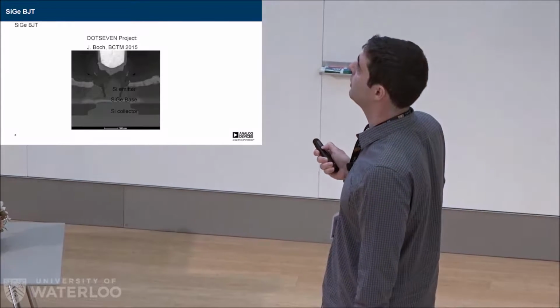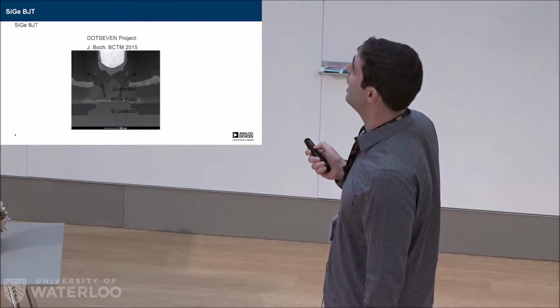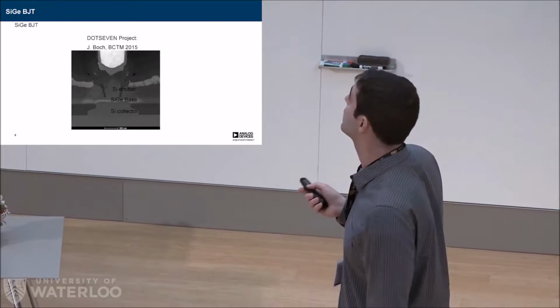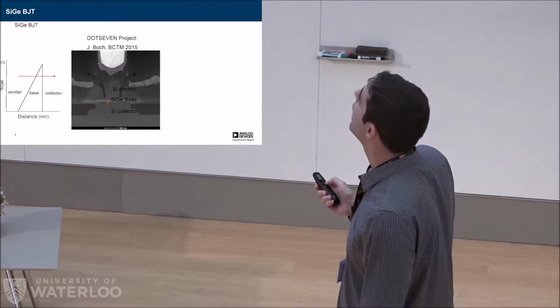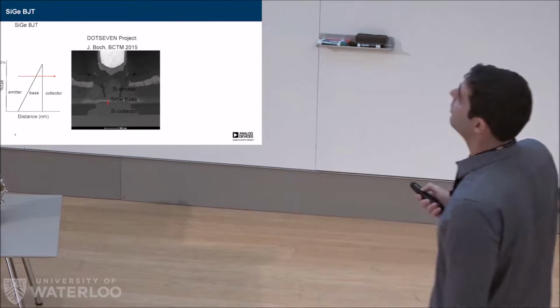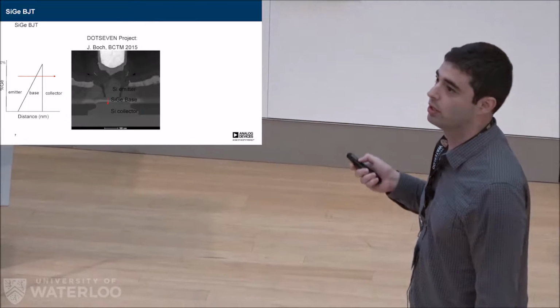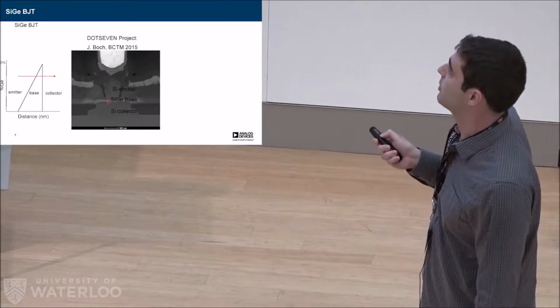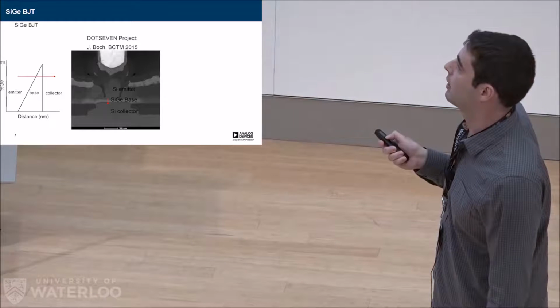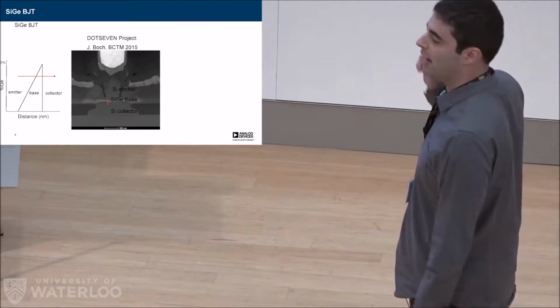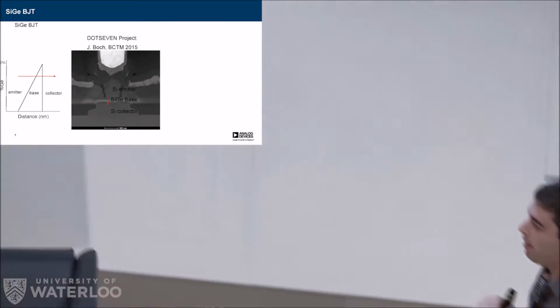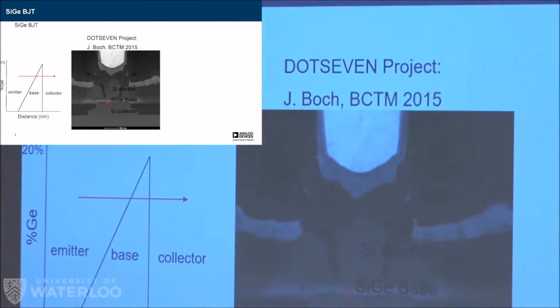So this is a completely different material, and you can see it's only about 10 nanometers thick or so in this image. And not only is it a different material, but it's actually got a graded concentration. The concentration of germanium starts really high, and then it gets smaller and smaller. So for this tiny little feature, every single layer of atoms, the subsequent layer has a few less germanium atoms than the previous one. Do you have any idea how hard that is to control? That is really hard to control.